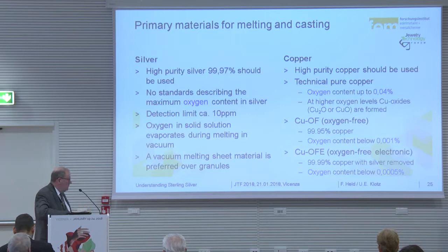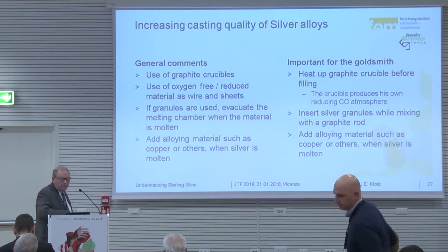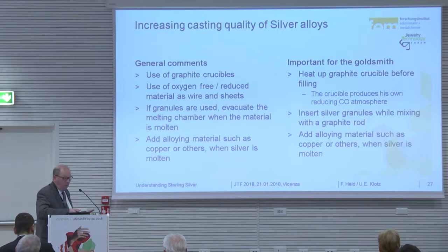So the general comments on increasing casting quality of silver alloy: use a graphite crucible, that's normal. Use oxygen-free reduced material as wire and sheets. I know it's easier to take granules, but if you use material which was molten before, the oxygen has left the silver. If granules are used, evacuate the melting chamber when the material is molten so that you take out all the oxygen of the silver, then add alloying material such as copper or other when silver is molten.